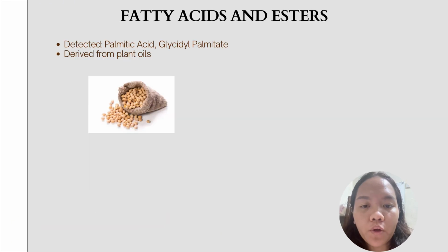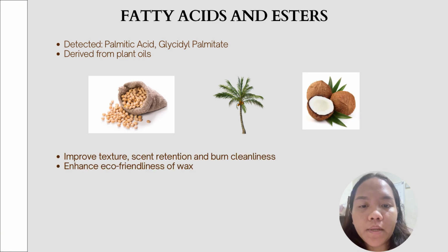We also found compounds like palmitic acid and glycidyl palmitate, which are derived from natural plant oils such as soybean, palm, and coconut. These fatty acid components not only improve the wax smoothness and scent retention, but also reduce soot and contribute to a cleaner, more